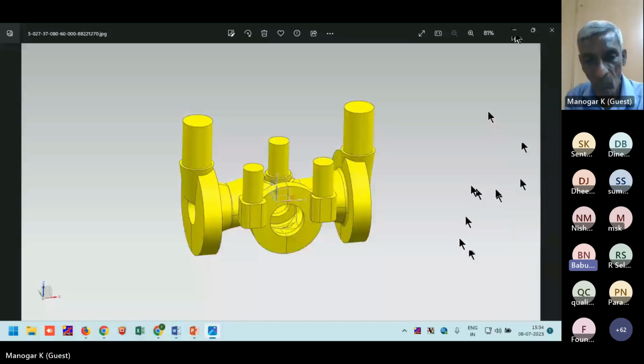Sir, what we are doing, going with modulus or feed metal requirement, take it as a low alloy steel. The feed metal requirement is 6%. Okay. So suppose it is a 100 kg casting, we can take 6 kg. Yes. So if it is going with sand casting, considering 10% efficiency for safety purposes for process variation, it is coming to 60 kg of sand riser, correct? So to that 60 kg sand riser, we are dividing by the 1.6 or 1.4, whatever the MEF specified by the supplier. You don't go by the MEF.